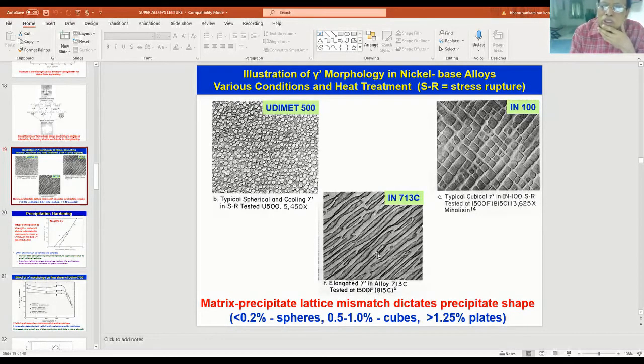This formation of gamma prime in different shapes will cause variation in the mechanical properties that you are looking for. For example, creep rupture life depends upon the morphology of your gamma prime phase and their volume fraction.